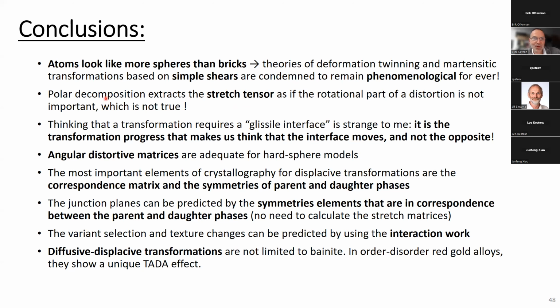If you use polar decomposition to extract the stretch tensor, you can do that. But please do not throw in the trash the rotational part of the distortion, because it is important. Actually, I do not understand why we need polar decomposition, or why we are so attracted by the stretch tensor. Thinking of a phase transformation as a glissile interface is strange to me. It's the transformation progress that makes us think that the interface moves, and not the opposite. We can use angular distortion matrices. They are quite adequate for hard sphere models.